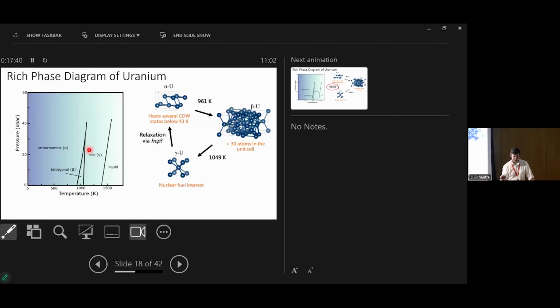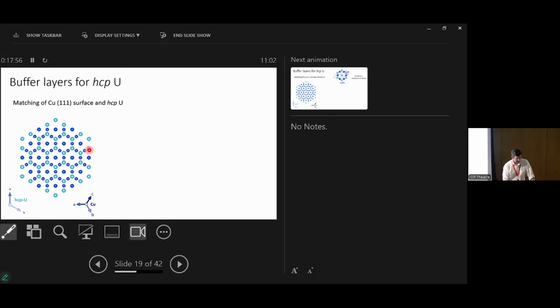And actually, there are a few examples in the literature where this HCP phase had been stabilized at the surface or in thin film form. And we wanted to go after this and understand the HCP uranium. So we had a really talented PhD student, Becky, and she discovered with a simple ball and stick model that if you take the copper 111 surface, this is the close packed surface, hexagonal close packed uranium would line up perfectly and be epitaxially matched to the copper 111 surface. So very small compressive strain. So the uranium should adapt to that and adopt this HCP structure.